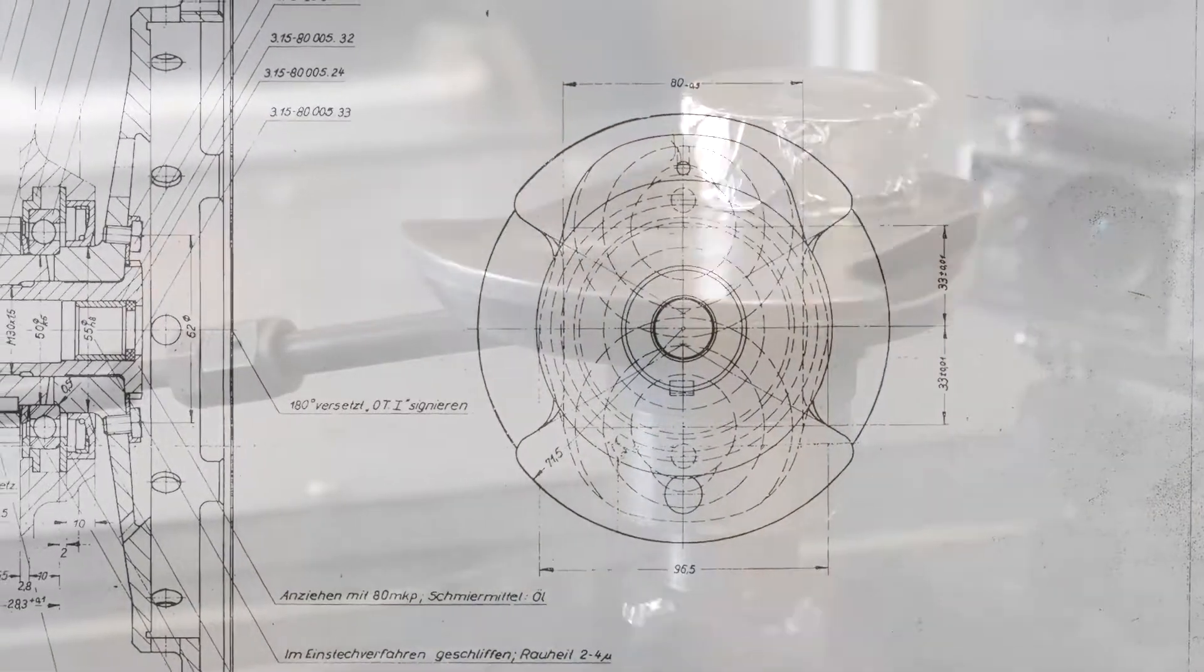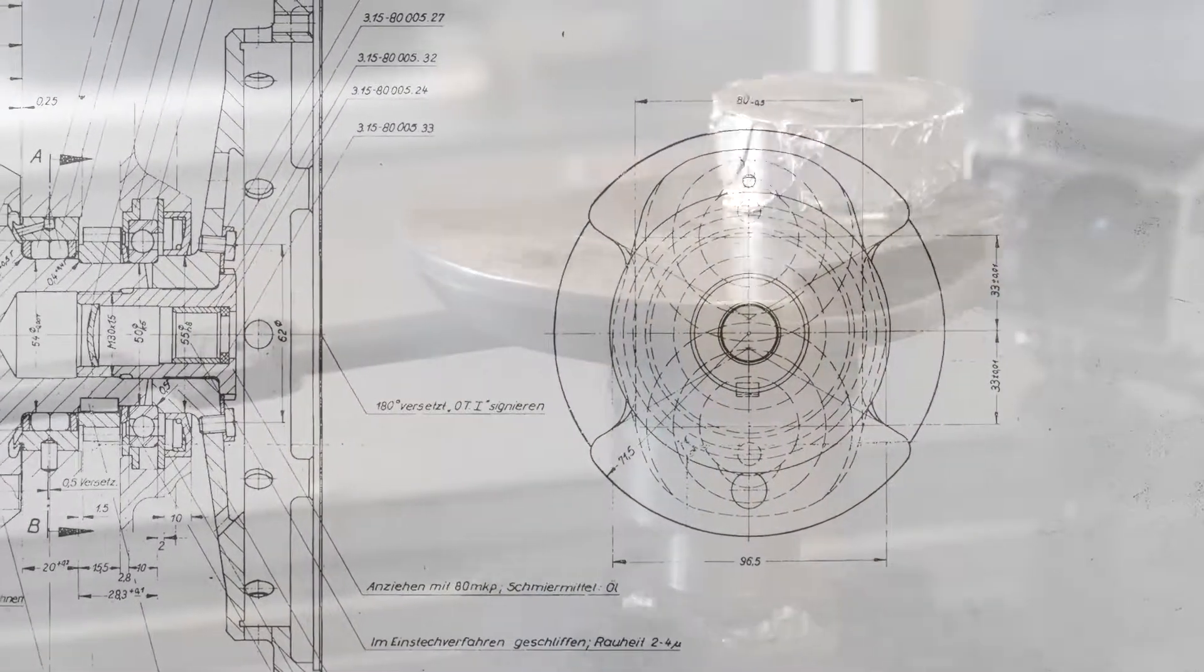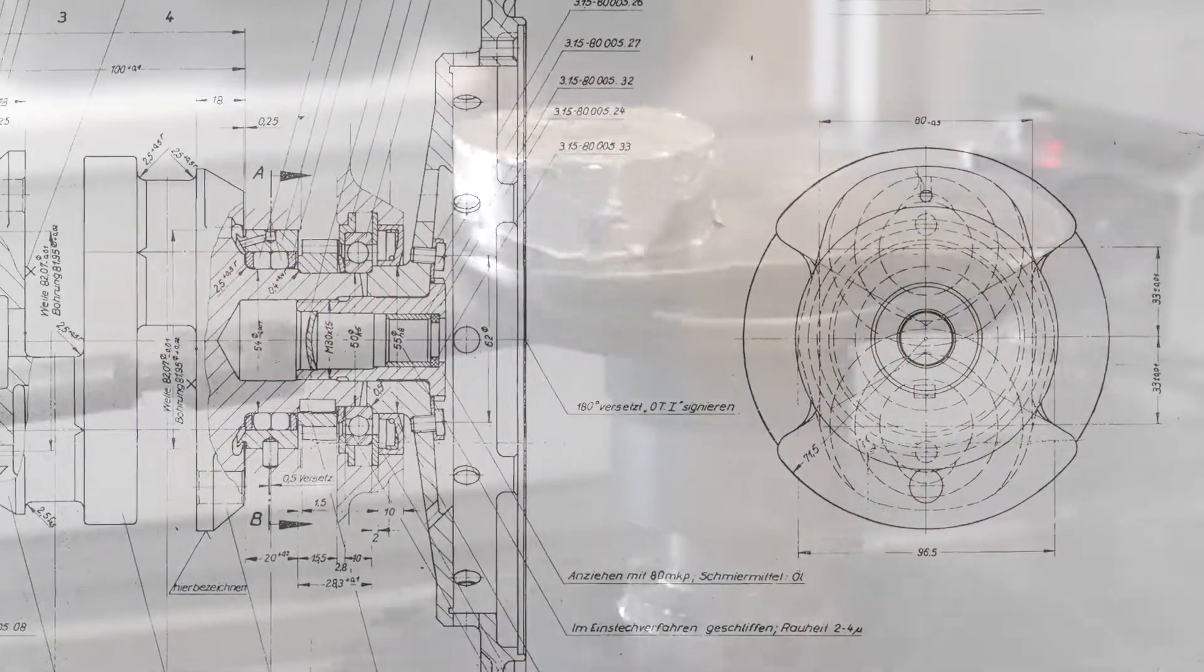Using the patented kinetic metallization process, Inovati was able to rebuild the bearing surface with a tungsten carbide cobalt coating, a far harder and more wear resistant material.